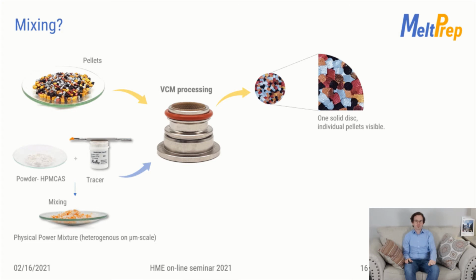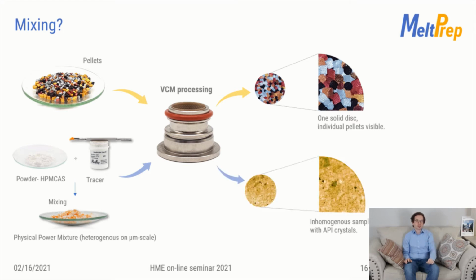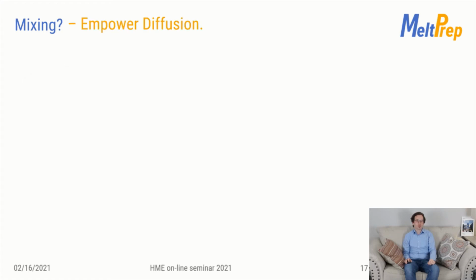We used an orange color dye on HPMCAS powder as a powder blend to illustrate that. As a result, a good fraction of the color tracer diffused already inside the polymer disc, but there are still some agglomerates visible. That's why homogeneous powder mixtures as a starting material are so important for our process. To improve the homogeneity, we have to empower diffusion by reducing the length scale further.